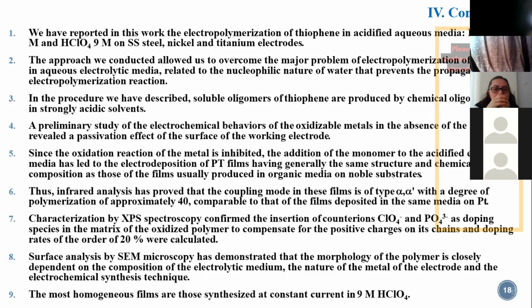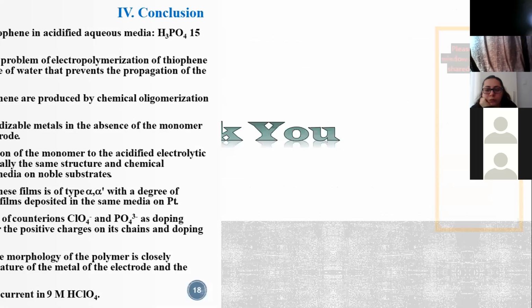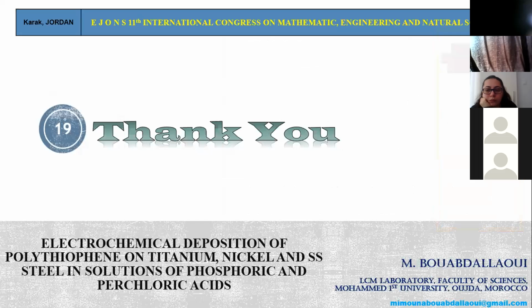Infrared analysis has proved that the coupling mode in this film is of type 2,5 with a degree of polymerization of approximately 40. The calculated doping rate is of the order of 20%. Surface analysis has demonstrated that the morphology of the polymer is closely dependent on the composition of the electrolytic media, the nature of the metal, and the electrochemical synthesis technique. The most homogeneous films are those synthesized at constant current density in perchloric acid. And in the end, thank you for your attention.